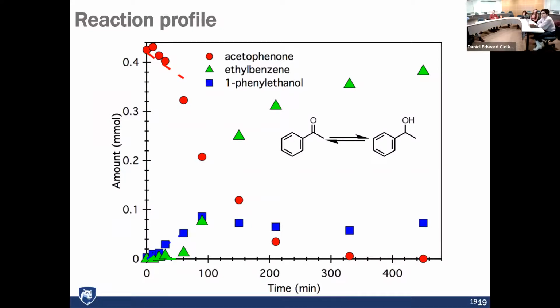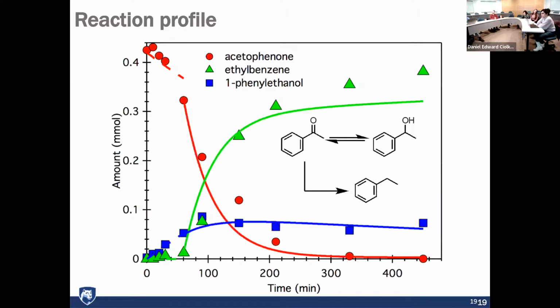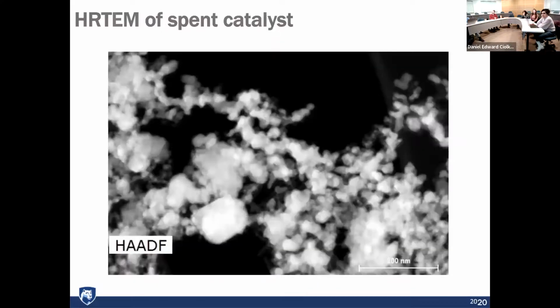And we do, the chemist in me says, oh, let's look at some kinetics of these reactions, trying to figure out reaction rates, how fast the reactions occur. And so we can see some information about the kinetics and how the reaction actually takes place, and potentially some mechanistic information. So what's going on the surface of our catalyst. Once you do the reaction, you could take another TEM image of your catalyst and try to see, did the catalyst change at all? Because remember, a catalyst is something that speeds up a reaction, but it doesn't change, so you can use it again.